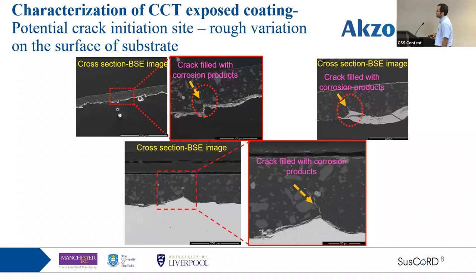As you can see in this low magnification image, we do not have any evident blister, but if we zoom in, we can see corrosion product has already formed and also a crack has developed here and filled with corrosion product. So I think here we can have two hypotheses that can justify this. One hypothesis is that the crack generates and then, due to the cyclic exposure, it propagates until it reaches the top surface and allows the environment to go in and the corrosion process to happen. And when corrosion starts, cracks also get filled with the corrosion products.